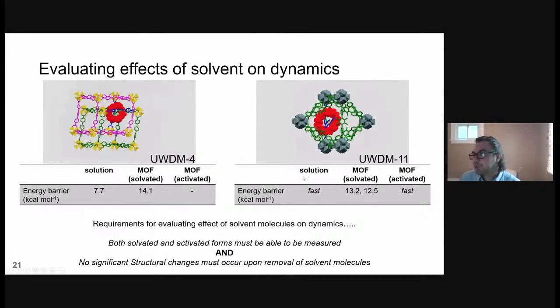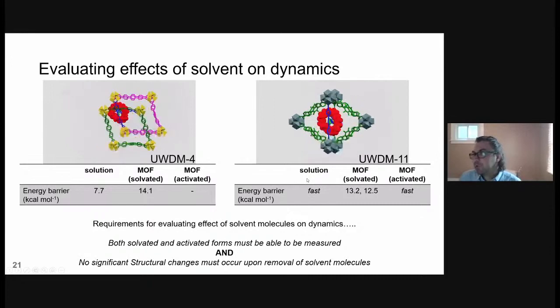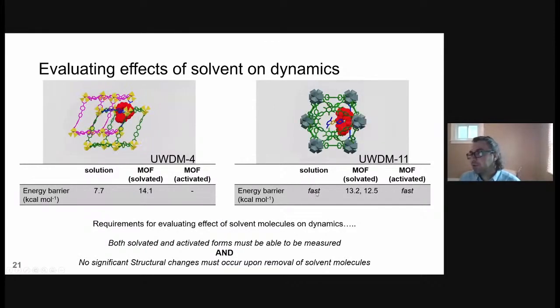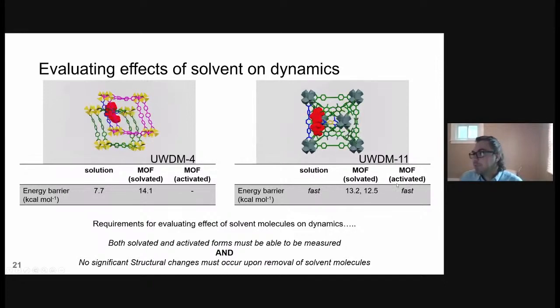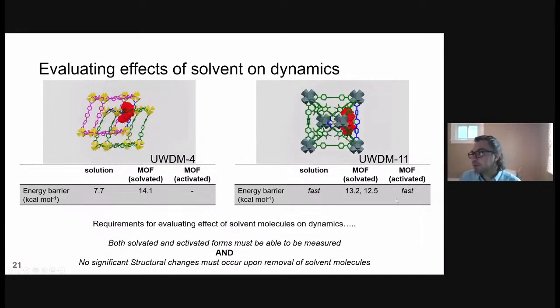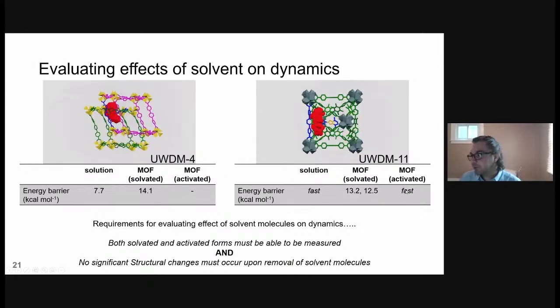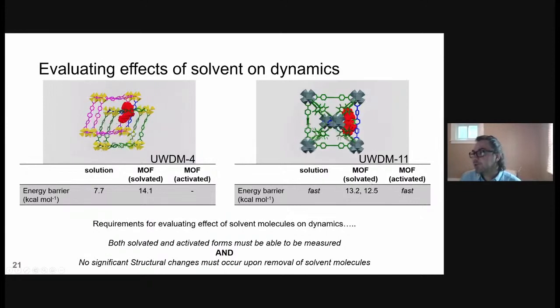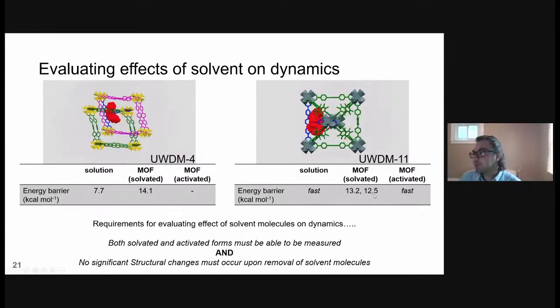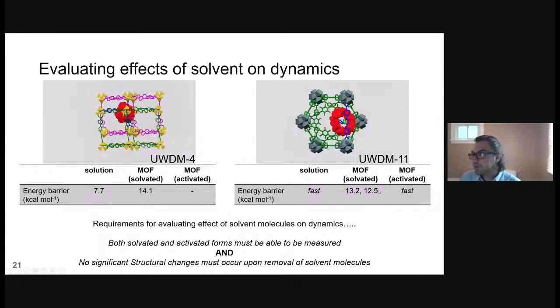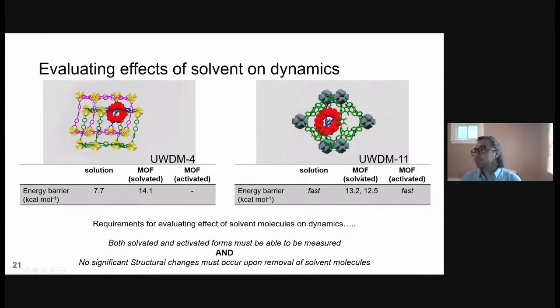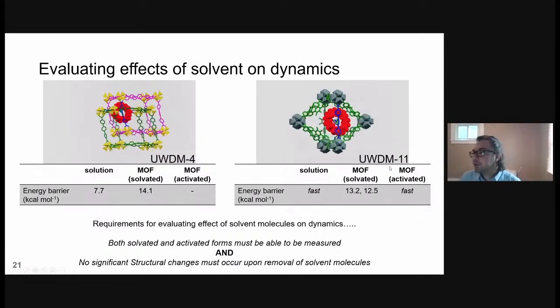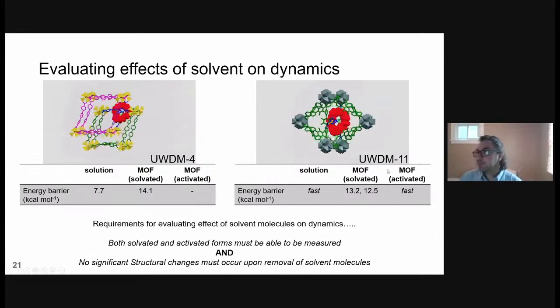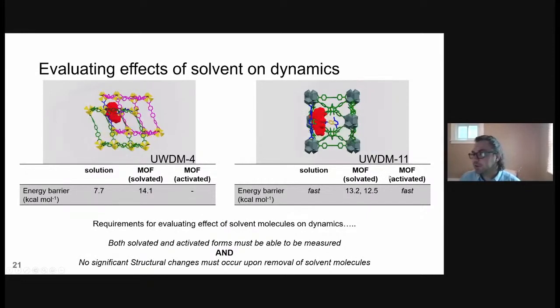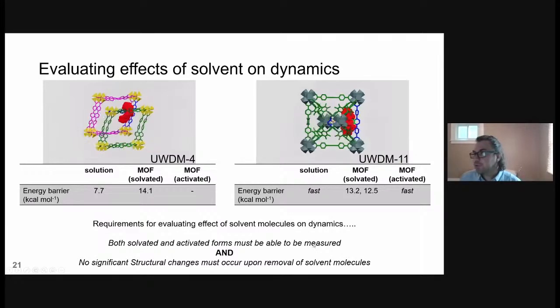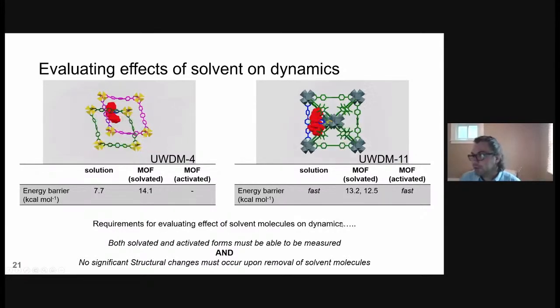However, with the zirconium system, while in solution, we weren't able to extract a rate. We simply know it's translating faster than the NMR timescale, even at the lowest temperatures. We were able to measure both the activated form, where once again, we knew the translational motion was fast, but we can't exactly quantify it. And then we could slow it down when we added the solvent and approximate these energy barriers here. So this is what makes this UWDM11 material quite nice in terms of evaluating dynamics, because it's very robust. We can measure both the activated and the solvated form without any significant structural changes occurring upon removing solvent or adding solvent.